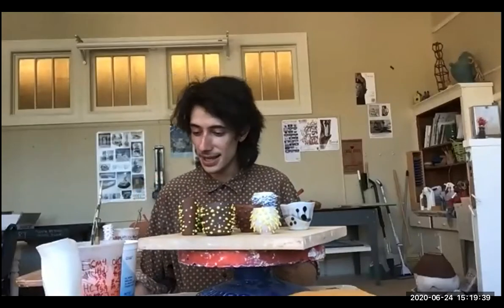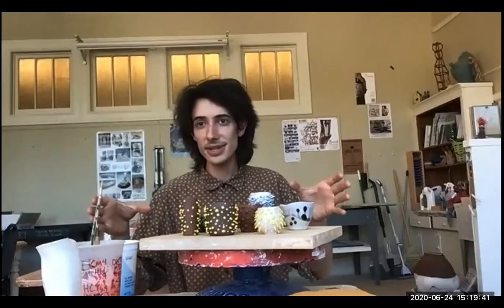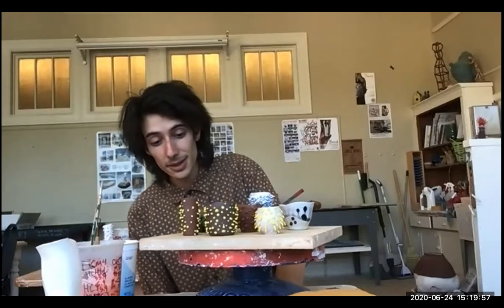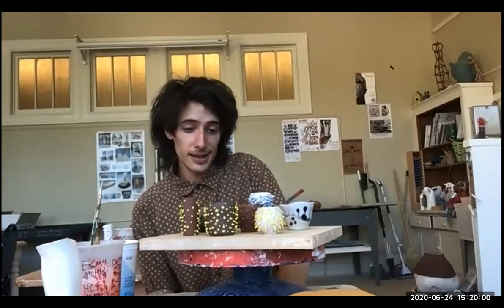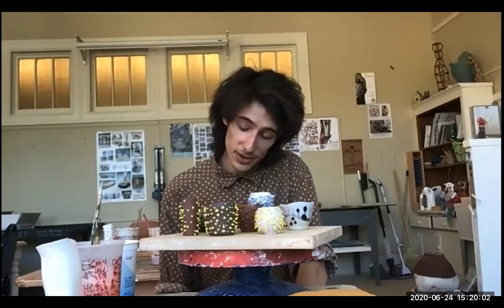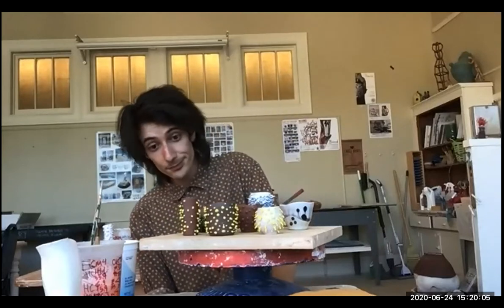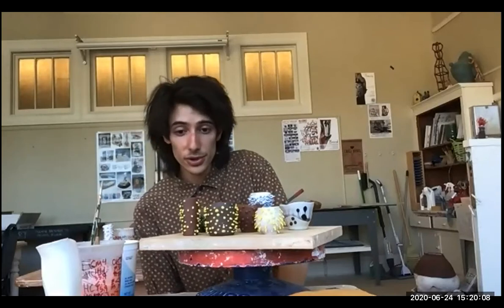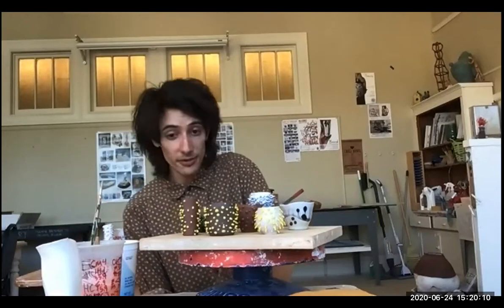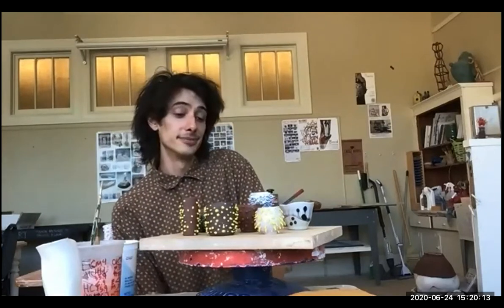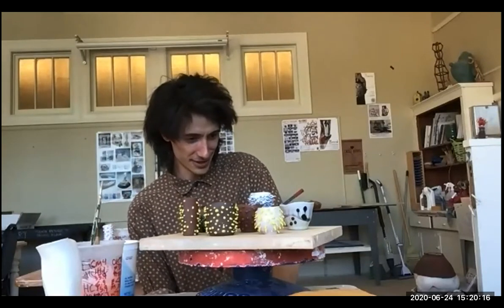And you can take a glaze and make 10 little batches of it and do a run, 0.25%, 1%, 4%, 8%, 15%, 30%, just to get a gist of how it's behaving with the glaze. And that's really the best way to develop these things, is try and be systematic, really dig into what individual materials are doing, or you can be systematic in the temperature, fire 1 to cone 3, 1 to cone 4, 1 to cone 5, 1 to cone 6. Yeah, a lot of ways to fool around.